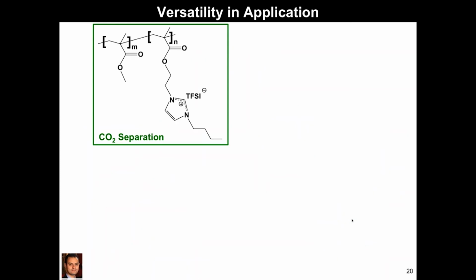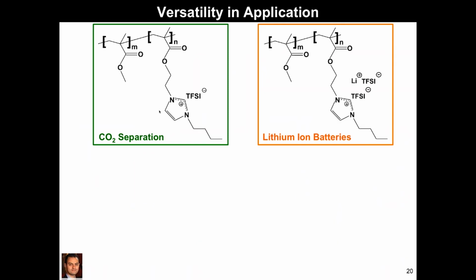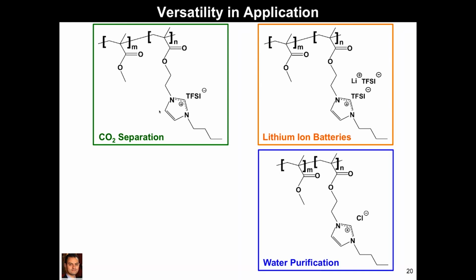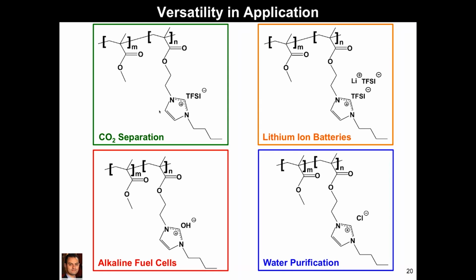A couple examples here. So the imidazolium TFSI here is well known to have high solubilities of CO2 over other gases. So some investigators have looked at these as membranes for CO2 separation. Also, several investigators have looked at doping these with lithium salts and using these as solid-state separators and binders in lithium-ion batteries. Also, you could think about different halides and think about water purification membranes. And then another application would be hydroxide as the counterion for application of alkaline fuel cells.